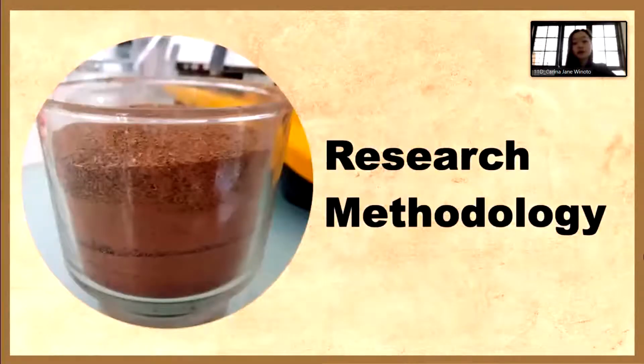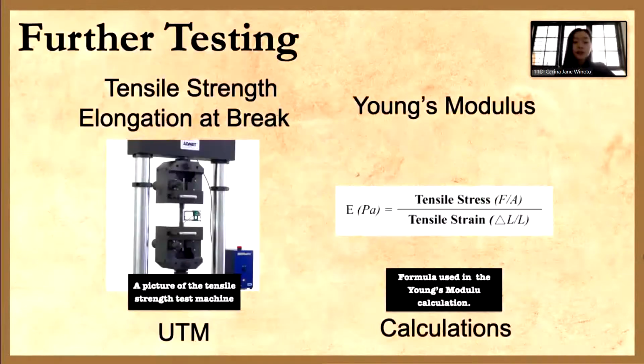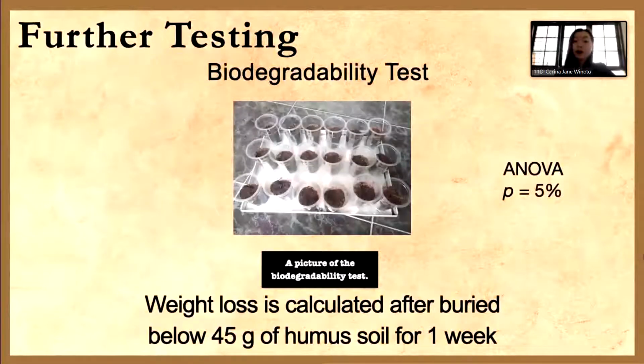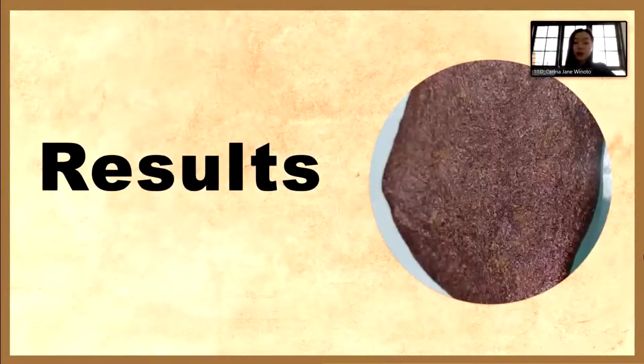Moving on to research methodology, further testing involves the investigation on samples' tensile strength, elongation at break, calculating its Young modulus value, and also conducting a biodegradability test in which weight loss is calculated after samples are being buried below 45 grams of humus soil for about 1 week. It is important to note that within such observations and investigations, each sample has 3 trials, and the results are analyzed with ANOVA probability 5%. Now, the results obtained were as follows.